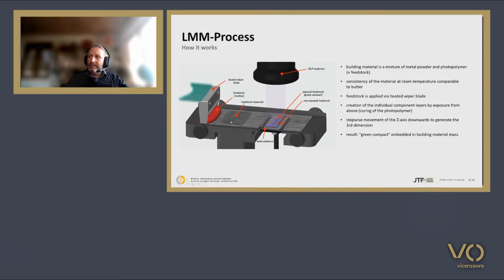So what you do, you have a feedstock reservoir, which you see here. I don't know if you see my mouse pointer. I'm painting on it. If you don't see it, the feedstock reservoir is written here. There, the material is deposited. Then we have a heated wiper blade, which is heated up to 80 degrees, which liquefies the material, and then you can make a very fine layer of this slurry, of this mixture of the polymer and the metal. And then in your print chamber on the build platform, you expose the whole thing with UV light, with a DLP projector from above, and then the material hardens where it's struck by light. Once you have exposed one layer, you go down one and do the next one. And the result is a green compact, which is embedded fully in this building material mass.